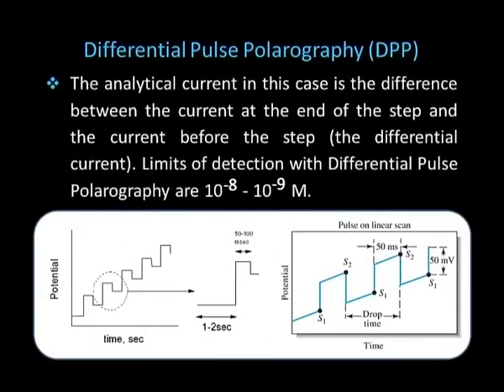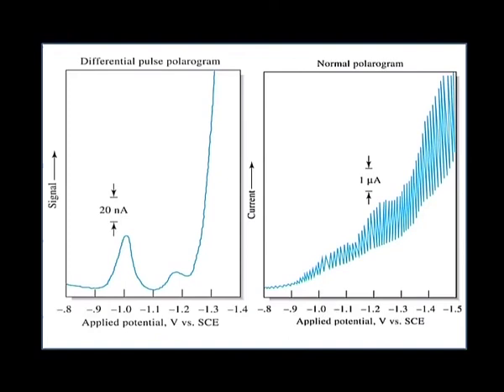The analytical current in this case is the difference between the current at the end of the step and the current before the step, and the limits of detection with differential pulse polarography are much lower in comparison to normal pulse or ordinary DC polarography. Here we can easily go down to 10 raised to the power minus 8 to 10 raised to the power minus 9 molar. Here you can see a differential pulse polarogram. Since we are plotting the change in current, or the difference in current, with applied potential, we get a peak in place of normal polarograms, which are S-shaped.